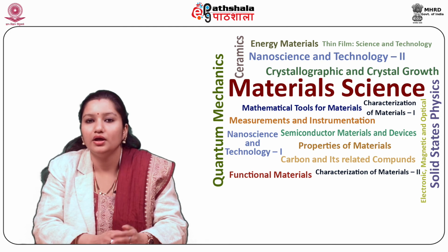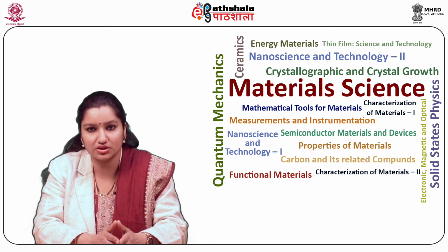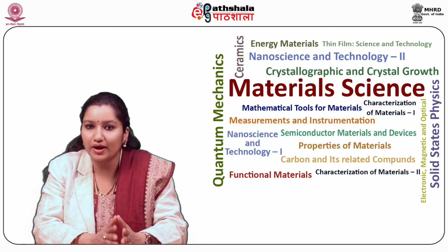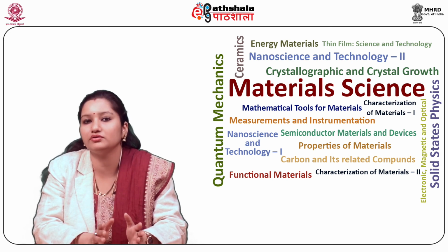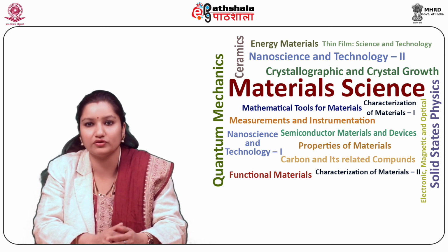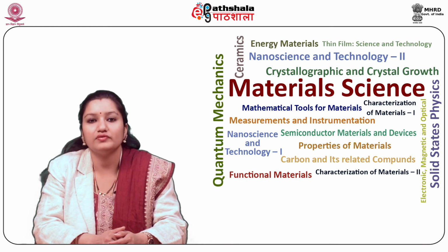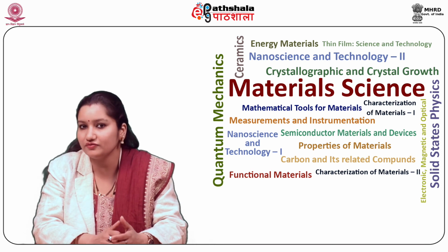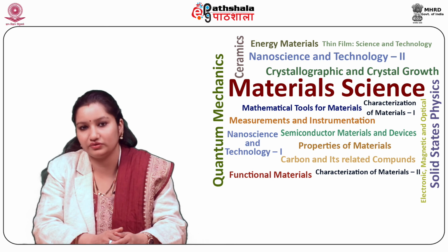More recently, advances in aberration corrector design have been able to reduce spherical aberrations and to achieve resolution below 0.5 angstroms at magnifications above 50 million times. Improved resolution allows for the imaging of lighter atoms that scatter electrons less efficiently, such as lithium atoms in lithium battery materials.